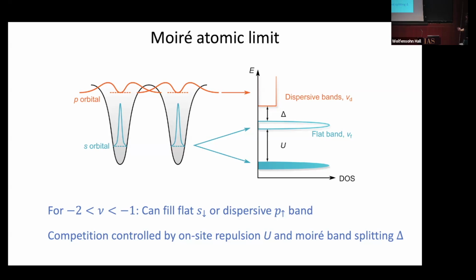These p orbitals, of course, can have also many different spin or orbital contributions. And so the key takeaway is that as you ask the question, what states do you want to fill past 1 hole per Moire unit cell, you have 2 options. You can fill this upper Hubbard band, or you could fill this more dispersive band. The details of the splitting between these are based on the microscopics of the problem. But on the other hand, you can tune with a magnetic field just from a Zeeman type effect. These will have opposite spin. These can have the same spin. And so as you change the magnetic field, you can tune the relative separation and energies of these different bands.